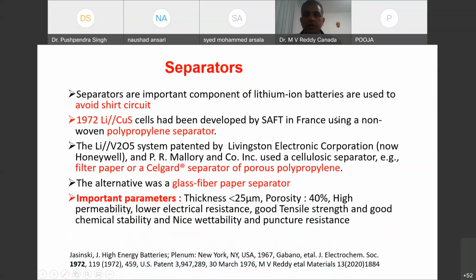Separators are important components to avoid short circuit, and we have to look for appropriate thickness, porosity, good permeability, low electrical resistance, and good tensile strength. It's very important once you make a big cell, because if by mistake your separator has some hole or puncture, that may lead to short circuit. Sometimes it may catch fire also. That's why it's very challenging. Everything should go through quality control, including the cathode, anode, electrolyte and separator.